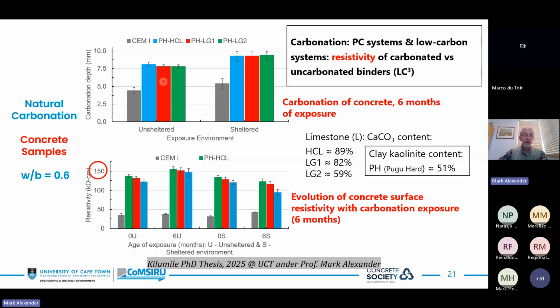And that's what happens. So here, the natural carbonation, this is 6 months. It's only 6 months, so it's very limited. We're waiting for the 12-month results. And here we got the LC3 calcined clay systems. And here you can clearly see that they're carbonating faster. Unsheltered, a little bit slower than in the sheltered, as we know, because of the presence here of moisture in the environment.